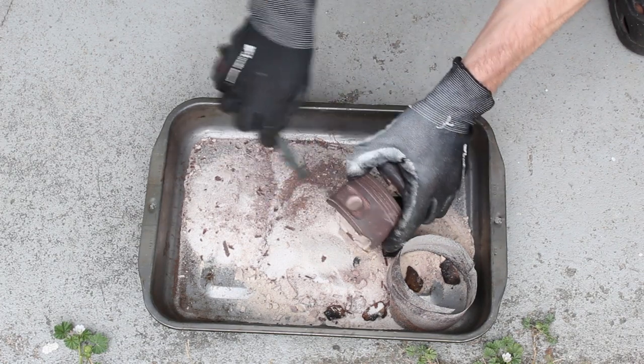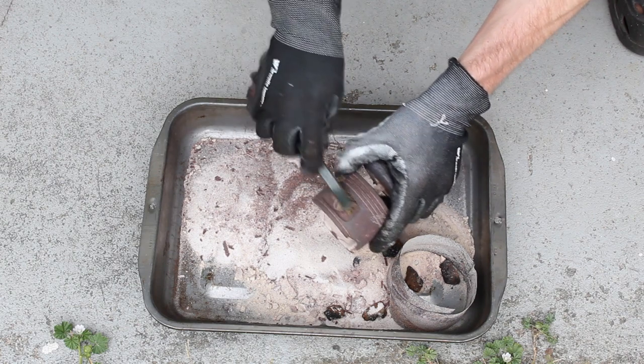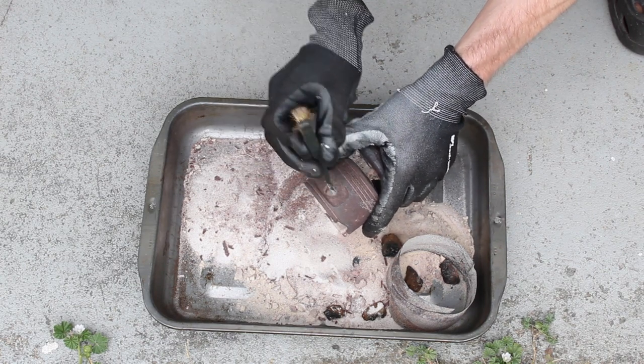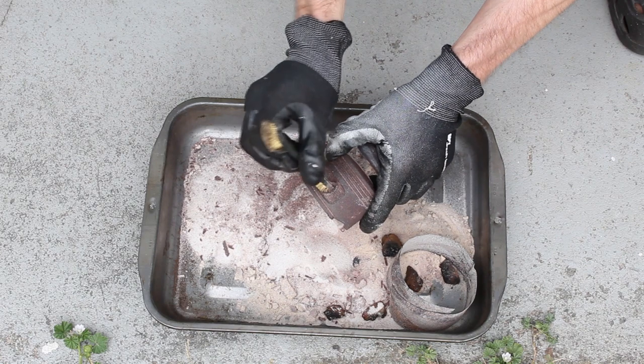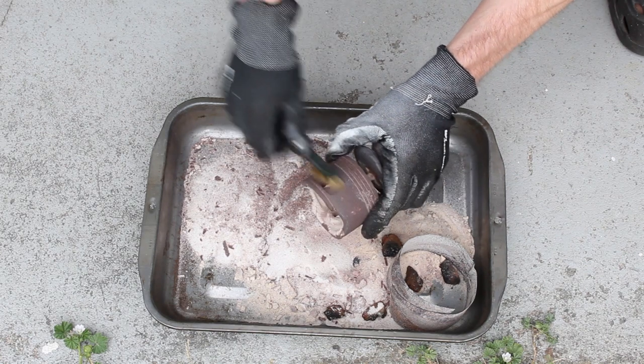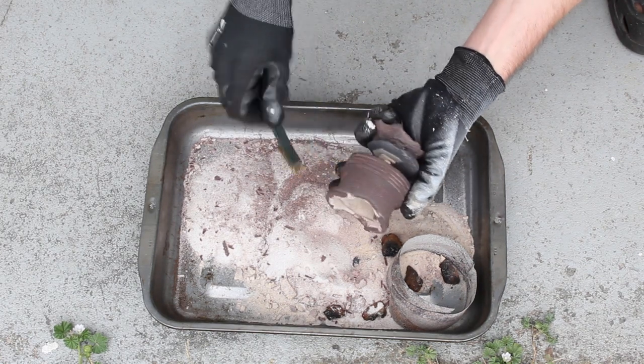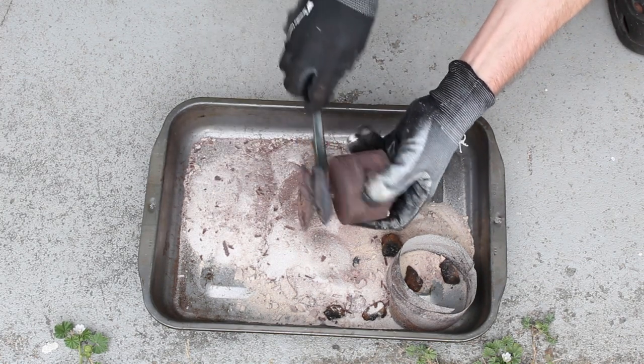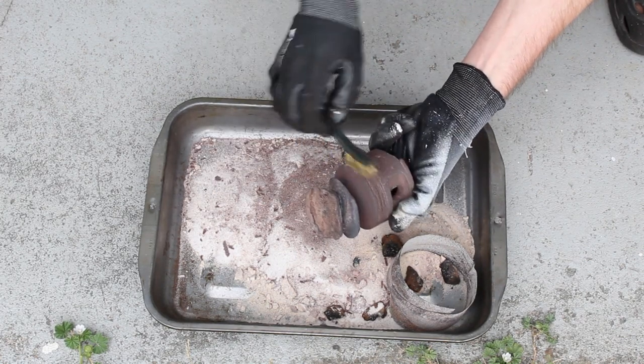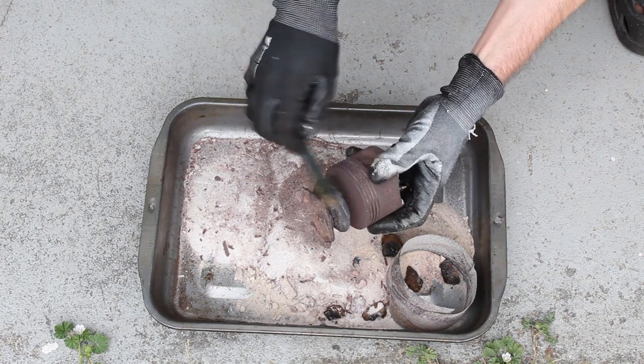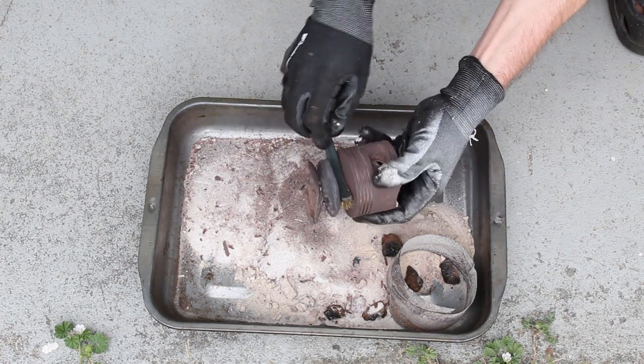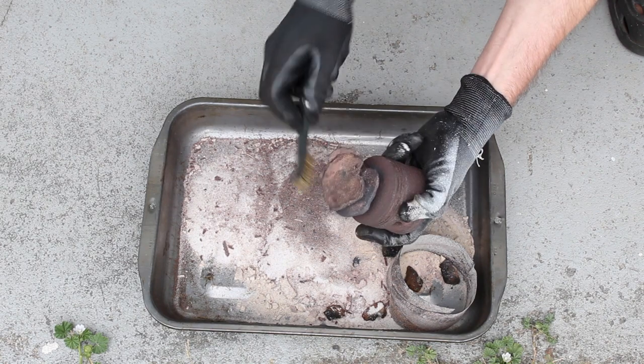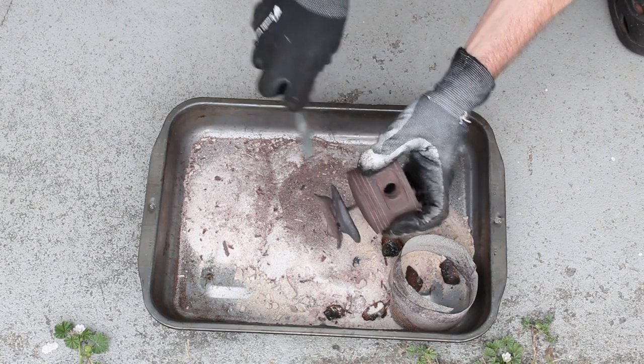If you're using high carbon steel instead of copper, you would need to use a higher temperature—probably something like 1250°C—and maybe hold it for three hours. The larger your crucible, the longer hold time you would need because it takes time for the heat to get inside the crucible.